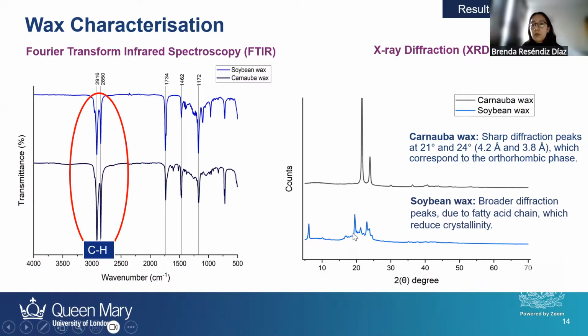But for soybean wax, we have similar peaks at 21 and 24, also at 19, but there is one peak before 10 degrees, which is related to the presence of fatty acids, which reduce the crystallinity in our material. So actually, soybean wax is more like a semi-crystalline or amorphous wax, compared to Carnauba wax in this case.